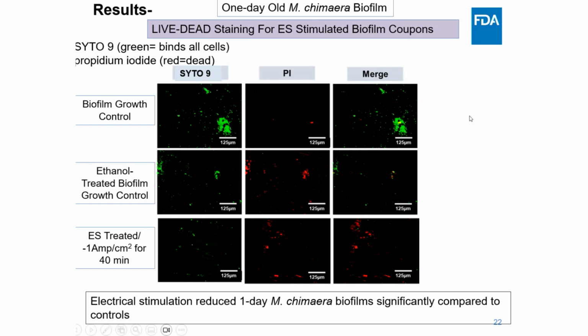In the growth control and ethanol-treated control, you can still observe substantial green fluorescence, indicating many viable cells remained, especially for the growth control, and we see some viable cells remain in the ethanol or chemical treated biofilm control. In contrast, the electrically treated sample shows an almost complete loss of green signal, demonstrating a significant reduction in live biofilm. This visual evidence strongly supports our colony count data and demonstrates that electrical stimulation can achieve a level of biofilm disruption not attained by ethanol alone, at least in the early stage of M. chimaera biofilms.